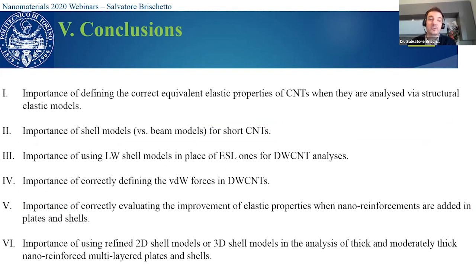Then we have seen also the importance of correctly evaluating the improvement of elastic properties when nano reinforcements are added in plate and shell structures. And finally, we have seen the importance of using refined two-dimensional shell models or three-dimensional shell models when we want to analyze thick and moderately thick nano-reinforced plates and shells, because we have several effects: the thickness effects, the in-plane anisotropy effect, and the transverse anisotropy effect.